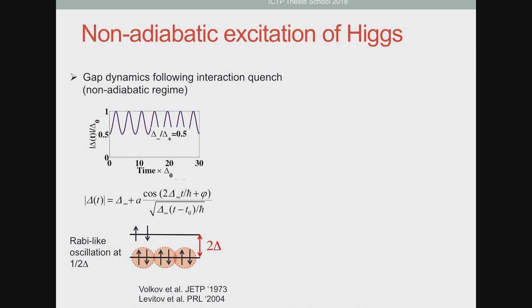These people could actually write down an analytical formula for the oscillation of the gap within the BCS framework. And what you can see is that, indeed, you have a cosine 2 delta t over h bar oscillation. And there is a 1 over square root of t decay that is essentially due to the Landau damping, to the fact that 2 delta is sitting right at the border of the electron-hole continuum. This is what is giving this 1 over square root of t decay.